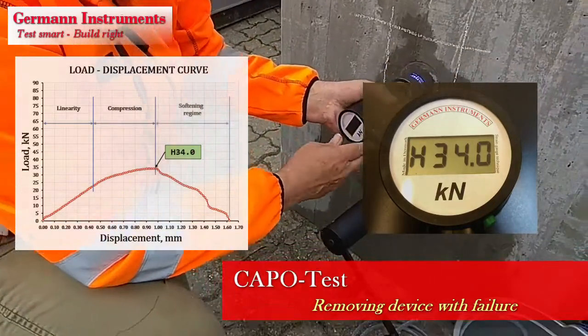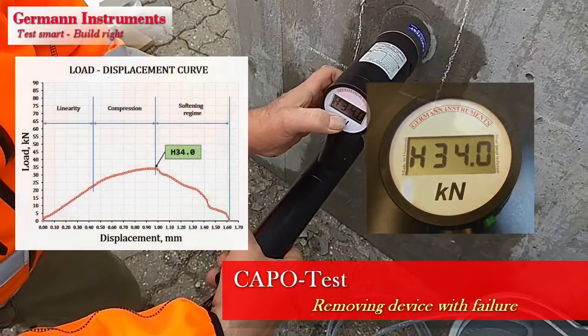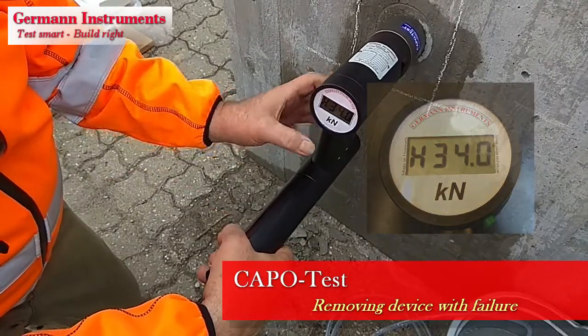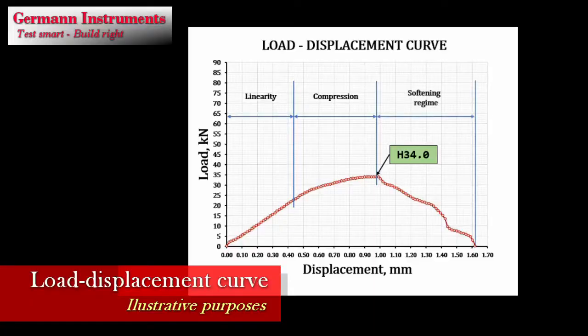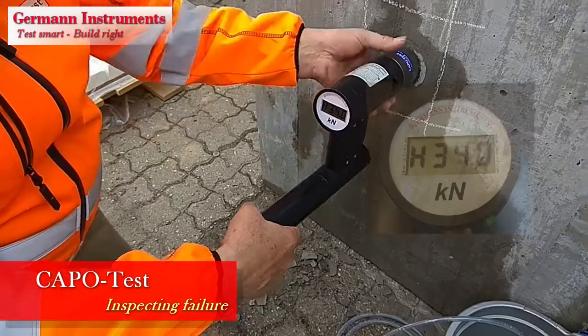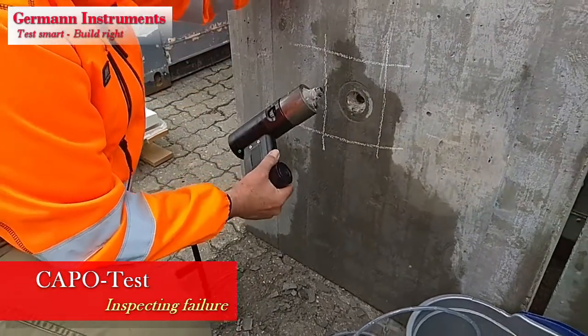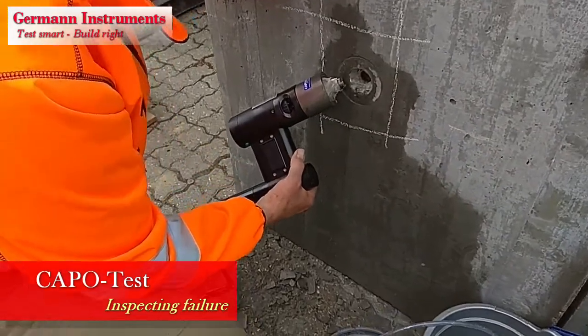The peak load is saved in the instrument's memory with date and time of testing as well for later printout and documentation. The load displacement curve is only shown for illustration purposes. Note that the curve is similar to the curve from testing compressive strength of standard laboratory specimens, clearly consisting of three parts: linearity, compression of the strut between the expanded insert and the counterpressure, and the softening regime producing the final pull-out cone. After the telescope handle has been loaded fully, the failure cone is extracted and inspected.